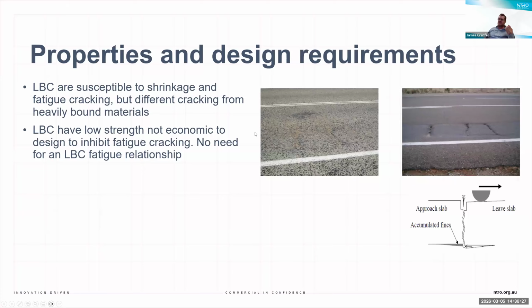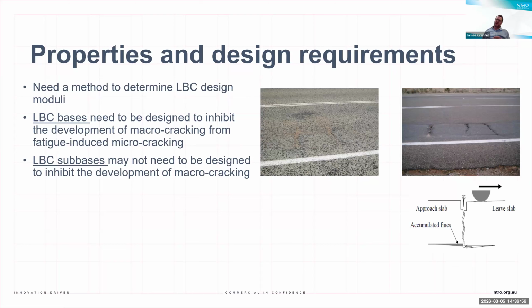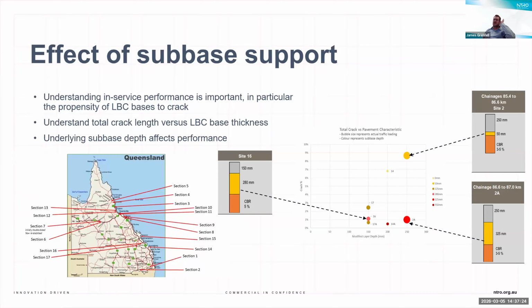These materials have a low strength, so they're not designed to inhibit fatigue cracking. We're essentially designing them as if they have a very limited bound life, and that they act essentially in a modified granular material state throughout their lifetime. And as part of this work, it was to develop a lightly bound cemented design methodology. A lot of the work was undertaken to try and characterize the materials and help us determine a design modulus at which these materials could be worked with in real pavement scenarios.